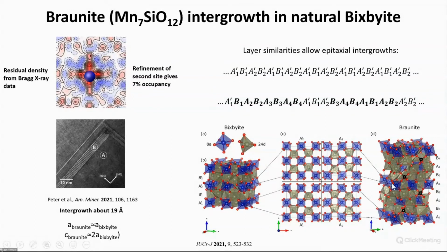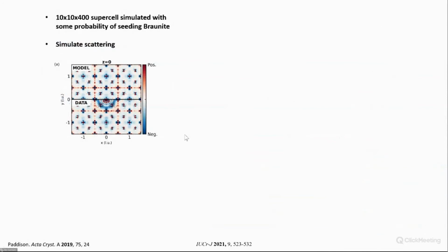So when the crystal grows and you maybe have a silicon matrix around it, it gets confused and gets this inclusion of braunite. And then when you're depleted, you probably go back and make Bixbyite. These intergrowths are about 2 nanometers. So another student, Christoph here, a brilliant student, said, okay, let me try to simulate it. He said, with some percentage chance, I will see the braunite layer. He built these gigantic 10 by 10 by 400 supercells and simulated these braunite intergrowths. And the scattering you get from this model is exactly identical to the diffuse scattering that you measure.